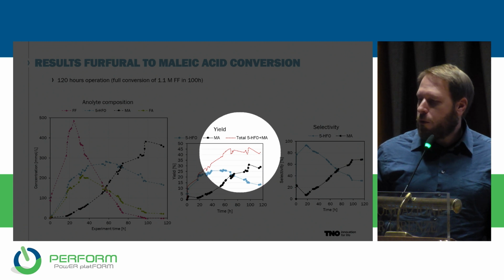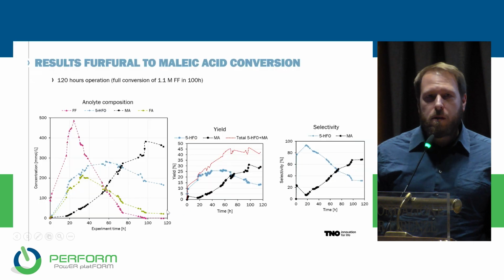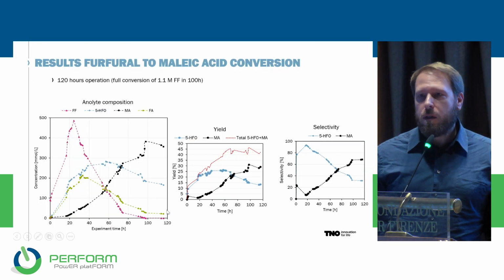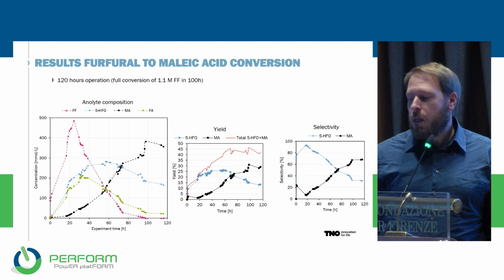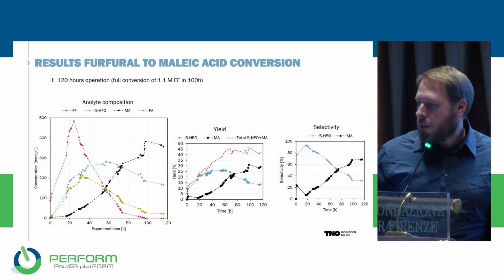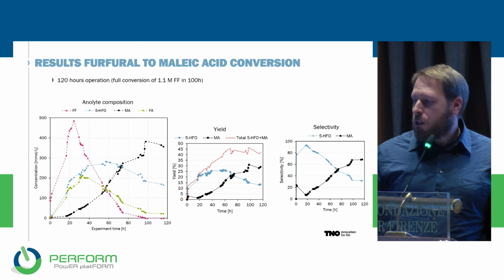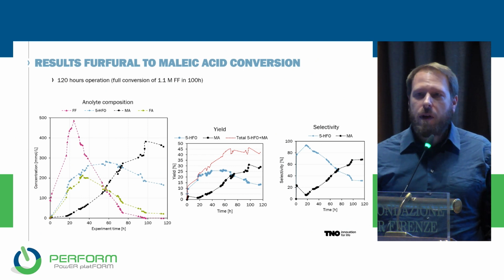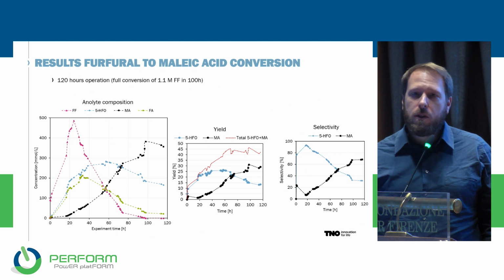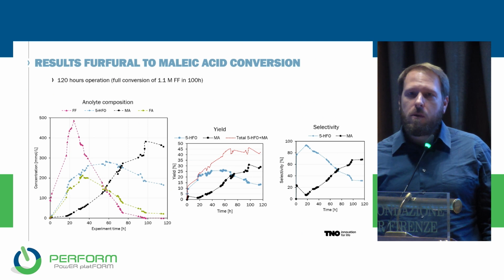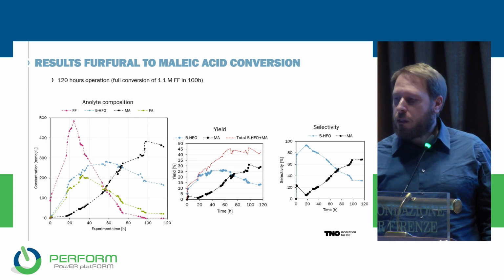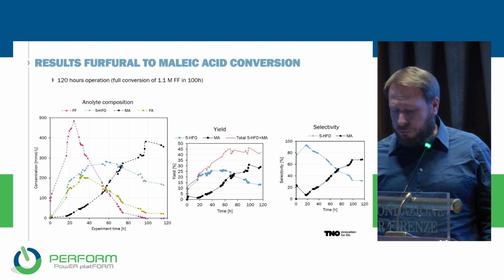However, we need to realize that we have about 45% yield, but if you look here, we run out of furfural. So this means that we are losing quite a lot of furfural throughout our process. And well, I can comment on that a bit later. But the fact that we actually get 5HFO is not a big issue, because we know that 5HFO is an intermediate in our reaction, and we can feed it back to our reactor in a second stage after downstream processes. So we can keep on converting 5HFO later on.